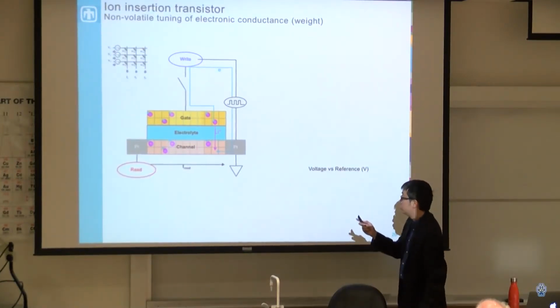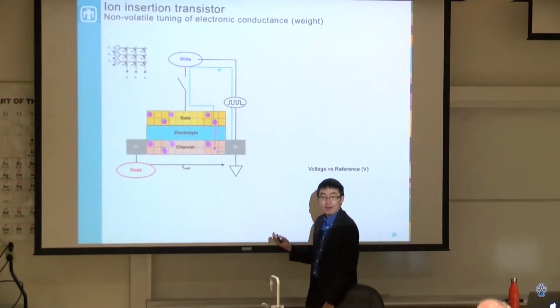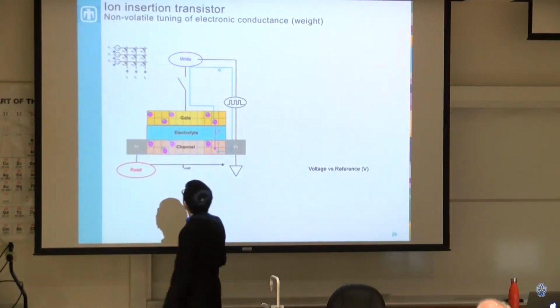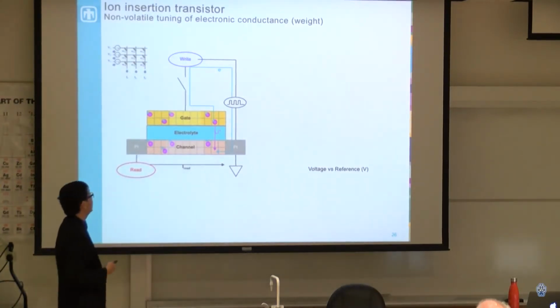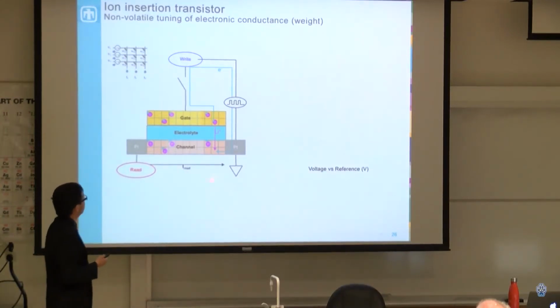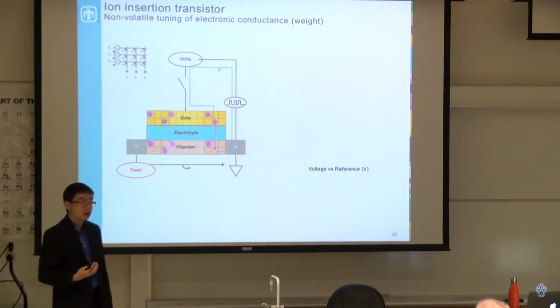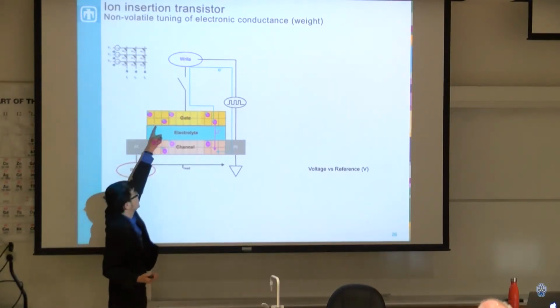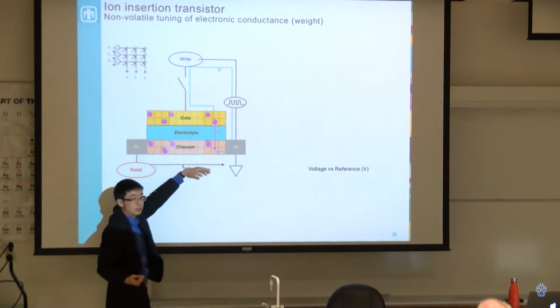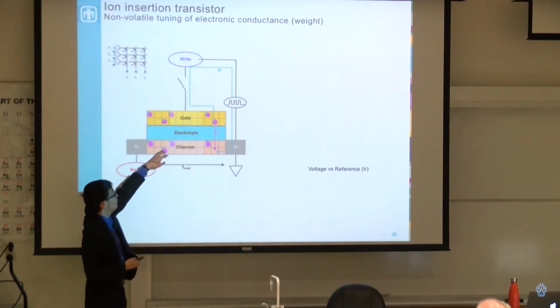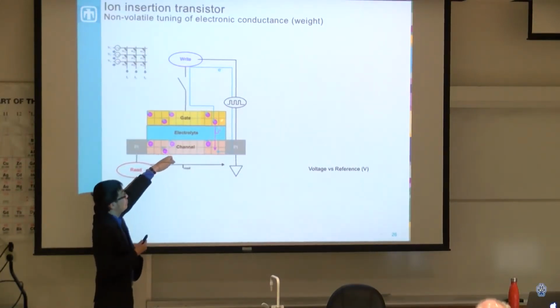And so basically what we do is that it's like a field effect transistor, except it doesn't work off electric field. So we call this an ion insertion transistor. And basically we're moving lithium between two materials, the gate and the channel. Whereas in a transistor you build up an electrostatic field here to modulate the channel conductance, here we're physically moving material, moving lithium ions from the gate to the channel.